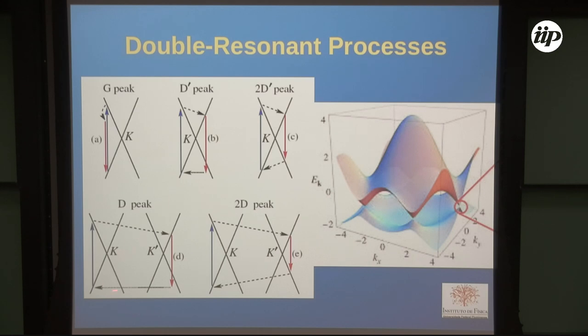What about the D peak? In the D peak, you have almost the same picture. We have a phonon with plus or minus Q momentum, and then the electron can be scattered back to here by a defect. So one of the scatterings is an electron phonon scattering, the other one is electron defect scattering. So that's why we have this if we have some kind of disorder in our system. Any kind of disorder can give rise to this kind of peak. And that's why the 2D peak has twice the frequency of that, because here I am measuring a Q momentum phonon in two Q momentum phonons, and here just one, okay?